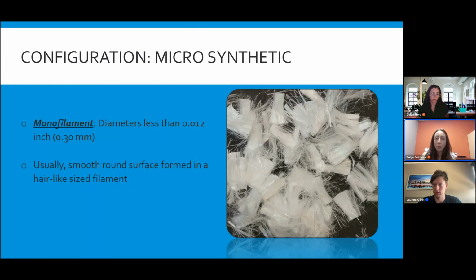First, talking a little bit about these micros. This is a residential fiber. It's typically dosed at 1 pound, and it's just used for plastic shrinkage to the surface of the concrete. So these can come in a variety of sizes, all the way down to 1/4 of an inch up to 3/4 of an inch. And these are things that you would see a lot in flat work.